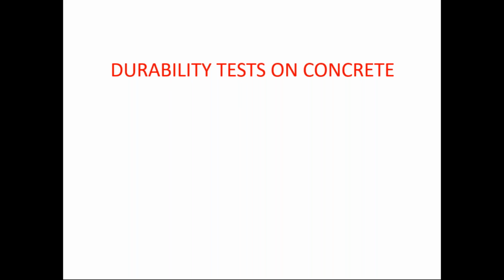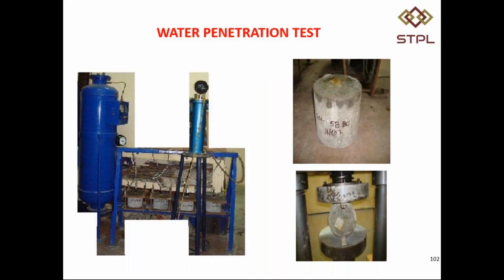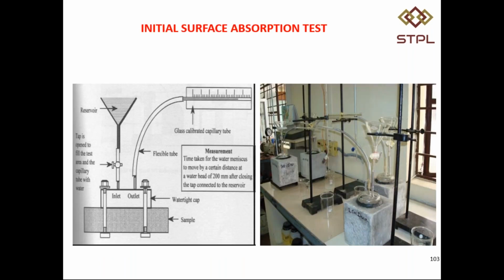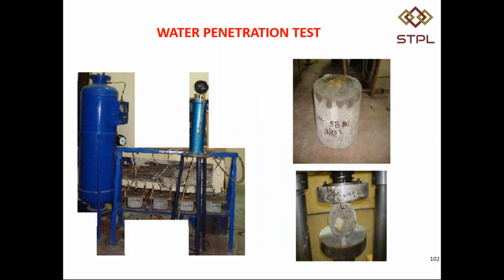So, durability tests are also done in the laboratory, which will give some of the durability parameters such as water penetration tests, wherein we will come to know how dense the concrete is which you have made using the aggregates, packing density, or the aggregate properties like that. So this water penetration test is nothing but the DIN water permeability test, wherein we apply a water pressure of about 5 bar continuously for 3 days, 72 hours, and then we take the sample and find out the depth of water penetration, how much water has penetrated into the concrete.